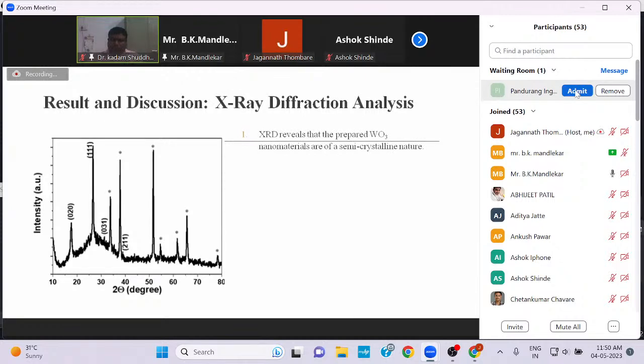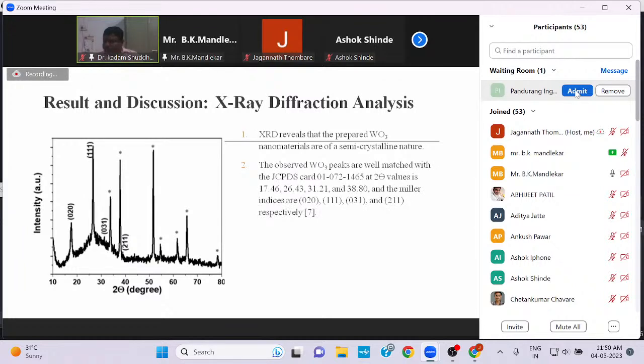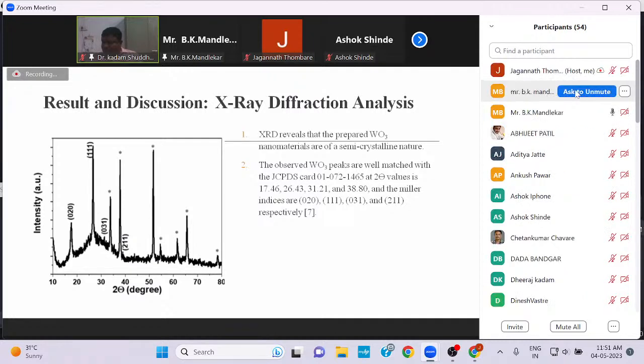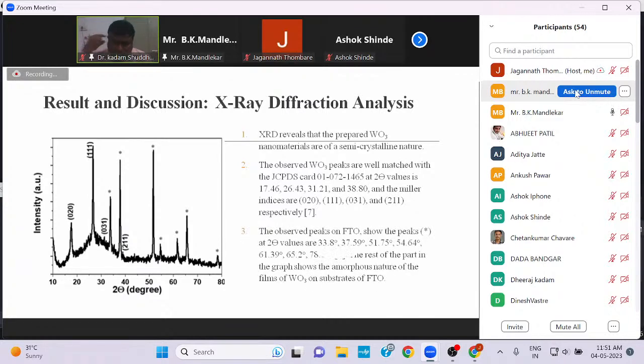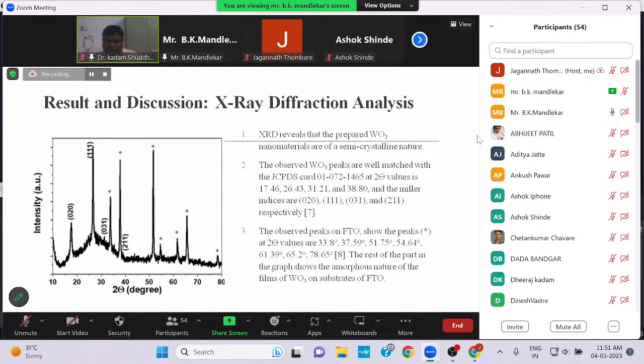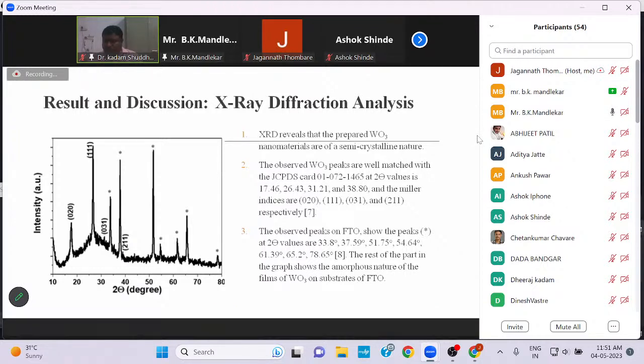What we found as a result: the X-ray diffraction revealed that the prepared WO3 nanomaterials are of a semi-crystalline nature. The observed WO3 peaks were well matched with this standard card at 2 theta values of 17.46, 26.43, 31.21, and Miller indices we observed 020, 111, and so on. The observed peaks of FTO also show peaks at 33.8, 37.6, and so on. The rest of this graph shows amorphous nature, and therefore we say that it is semi-crystalline on FTO substrate.